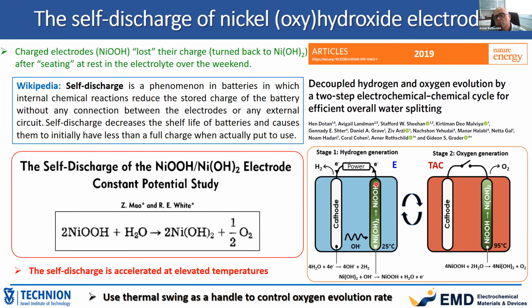Then we stop the system. We switch the electrolyte from low temperature electrolyte to a high temperature electrolyte, so from ambient temperature to near boiling point temperature electrolyte. And then there is a very fast spontaneous reaction that involves oxygen. So with this, we get two advantages. One, there is no membrane here, okay? We decouple the oxygen evolution reaction over time. So part of the time, the cell produces only hydrogen, and another part produces only oxygen.